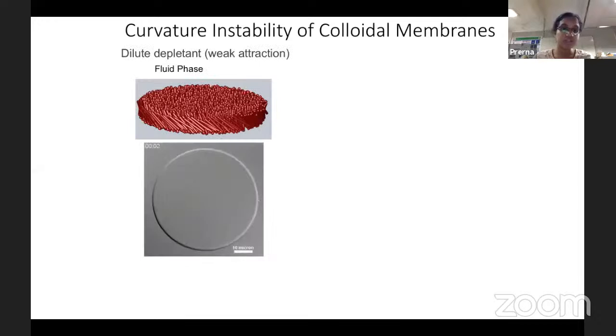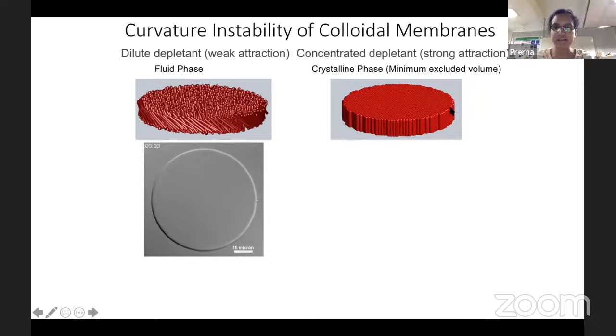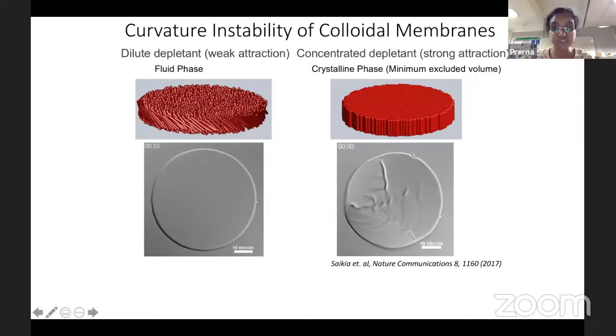Another example where chirality really introduces shape instabilities is in the context of crystallization. So I had shown you these fluid colloidal membranes whose edges fluctuate, which do not have any positional order. So the question that my lab asked was very simple. What happens when you increase osmotic pressure so that you get formation of a crystal? In other words, we were hoping to get a flat crystalline sheet, but what we actually found out was that the sheet was highly buckled and wrinkled. So the whole study was really trying to figure out how this instability comes about. I'll spend two to three minutes more talking about that, and then I will conclude.